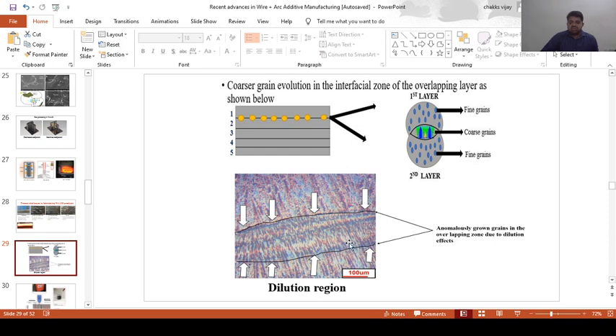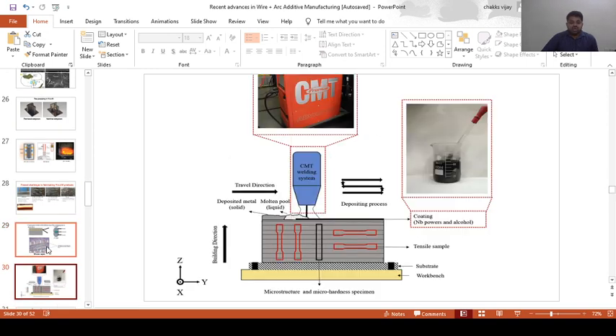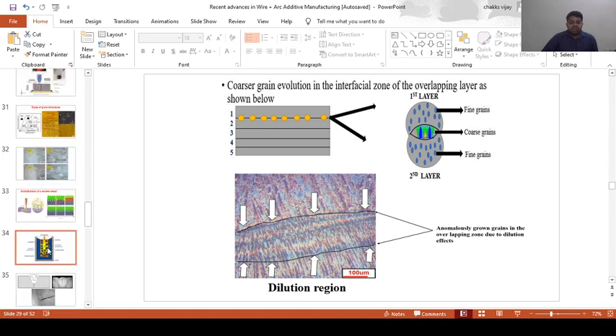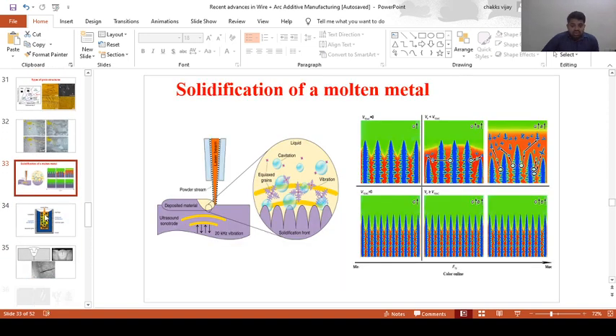So this is a dilution area. In this particular dilution area, grain coarsening is more likely, which will lead to failure. Mostly these are the potential sites for crack nucleation. In order to work on that, we generally go for a rolling operation at the end of each layer deposition, which I have mentioned over here.